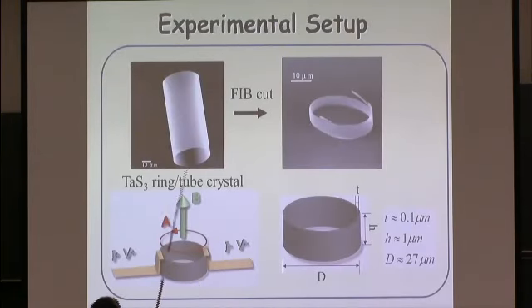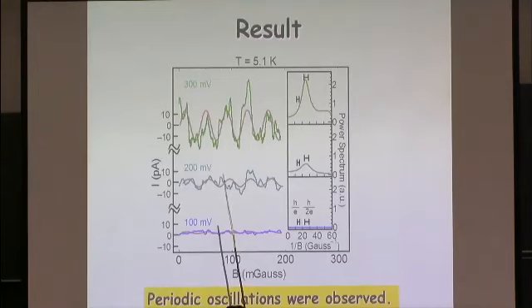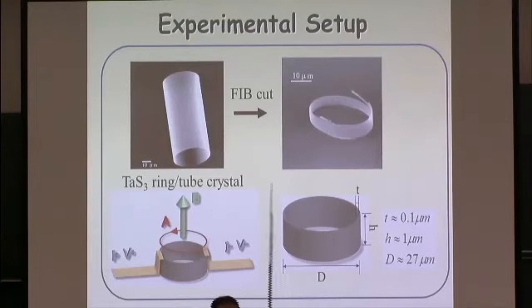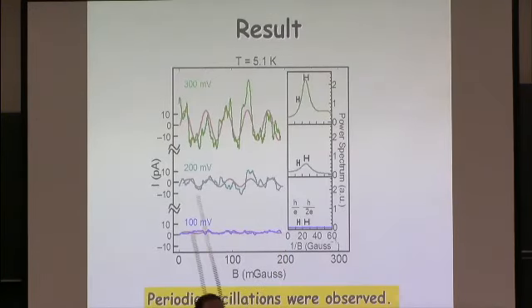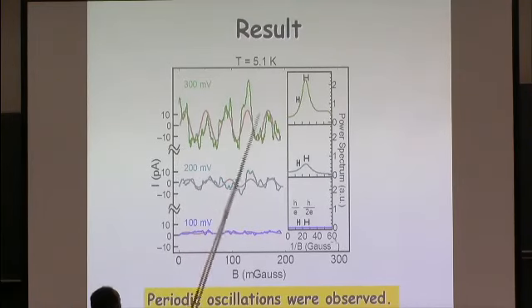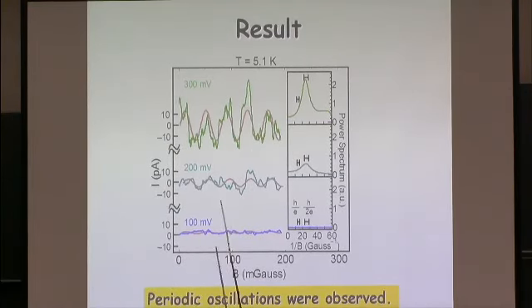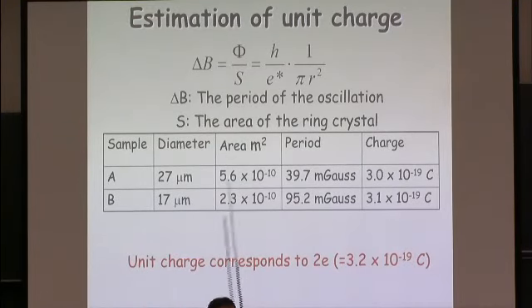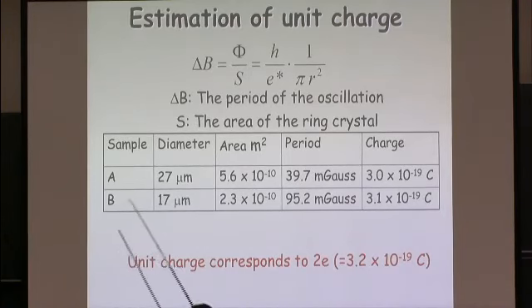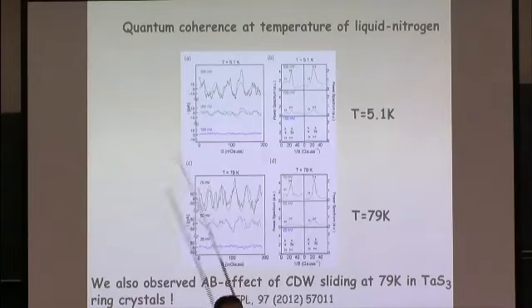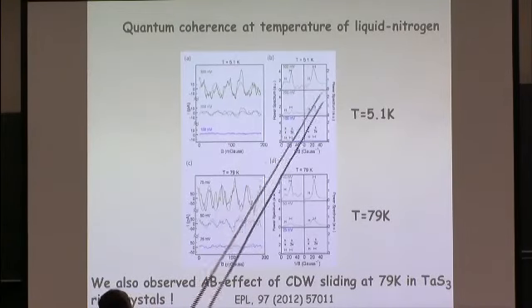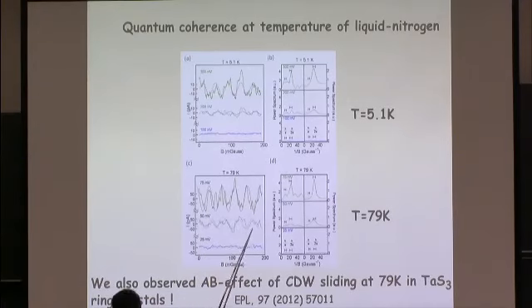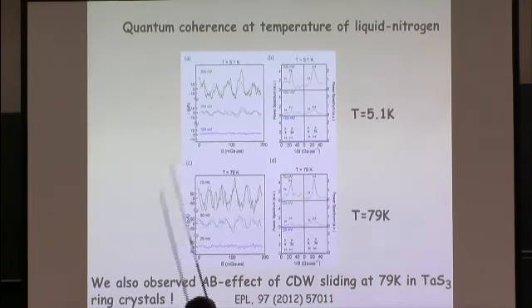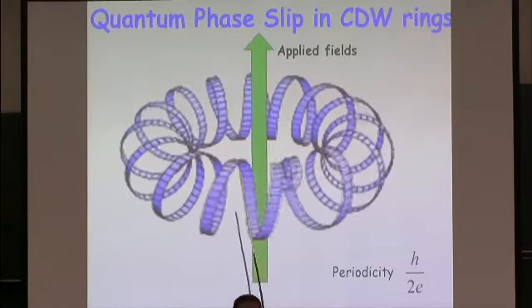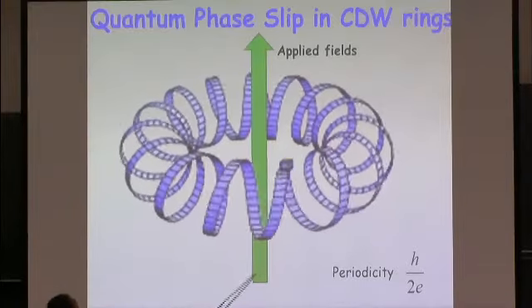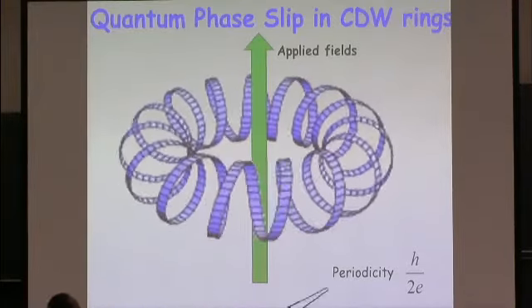Next, we observe the AB effect of charge density wave. We use the ring crystals and electrodes like this figure. And we obtained oscillating peaks. Periodic oscillation was observed. And we estimate a unit charge. Unit charge corresponds to 2e. And recently, we observed quantum coherence at liquid nitrogen temperature, like this. We also observed it at liquid nitrogen temperature. We propose a quantum phase slip model in charge density wave, with applied field and phase slip and periodicity h/2e.